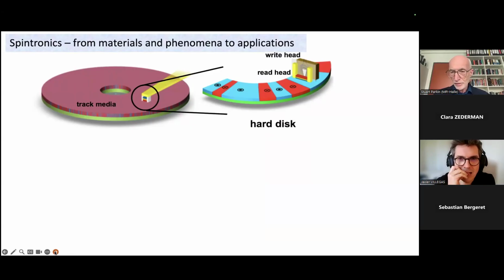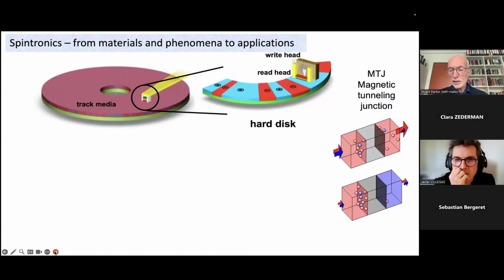And these stray fields are very tiny, but they can be detected using a spin valve structure that actually I invented when I was at IBM in the late 1980s and early 1990s. And IBM first introduced this device into a magnetic disk drive in 1997. But in 2007, the basic sensing device is the same, but the physics switched from spin-dependent scattering at interfaces to spin-dependent tunneling in a tunneling junction.